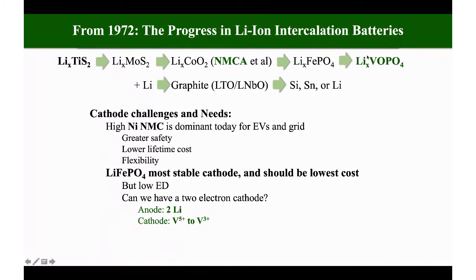I've already discussed these cathodes. On the lithium side, graphite is, say, dominant, but some of the Japanese companies are making, I would say, very high rate, safe batteries using lithium titanium oxide or lithium niobium oxide. When this is combined with lithium iron phosphate, you've got basically a 2-volt system, but very long lived.